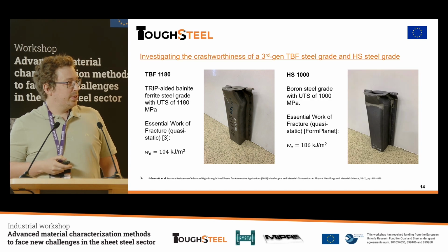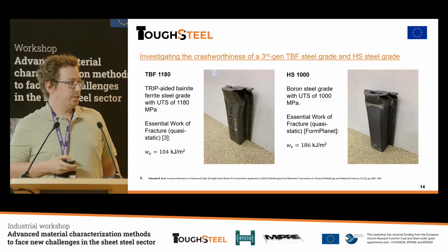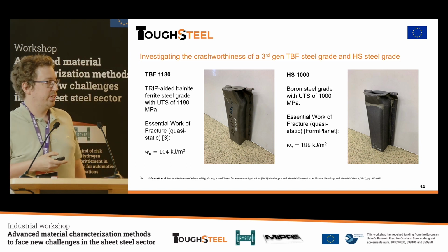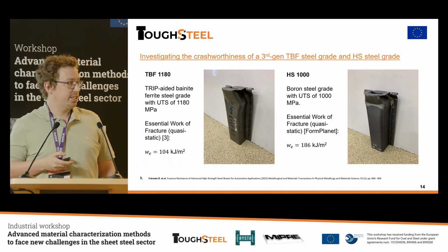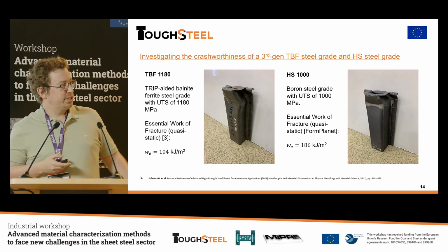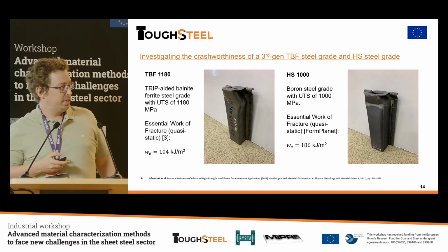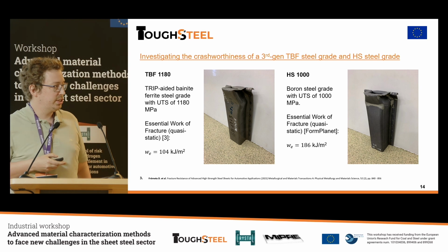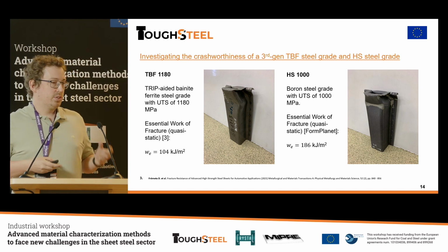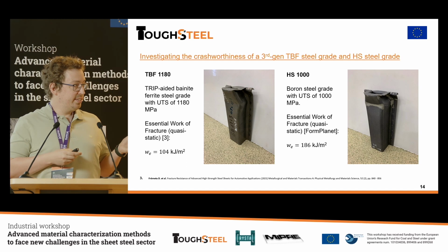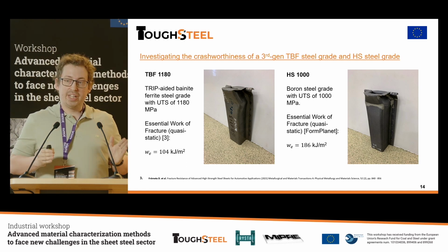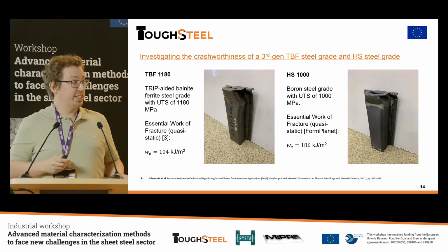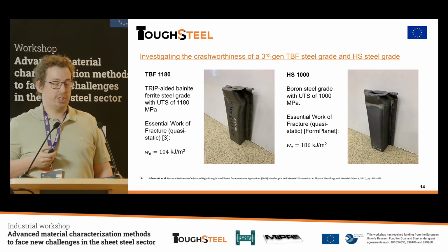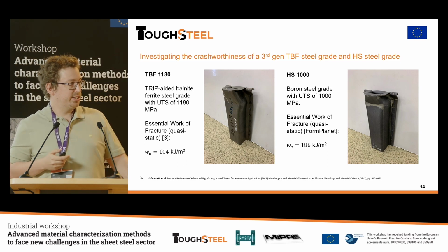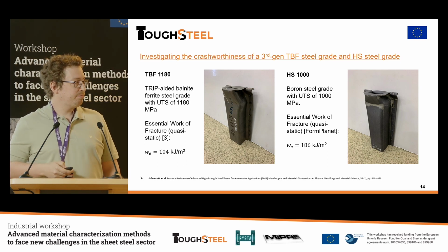And also we had a hot stamping steel. It's a boron steel grade with an ultimate tensile strength of 1000 megapascals. And I found this from our Horizon project, the FormPlanet project, and we found the essential work of fracture of 186. So as you remember from the last slide, before doing any experiments at all, we should expect the right one, the hot stamping steel, to perform better when it comes to crashworthiness than the left one, because we have a higher essential work of fracture value there.